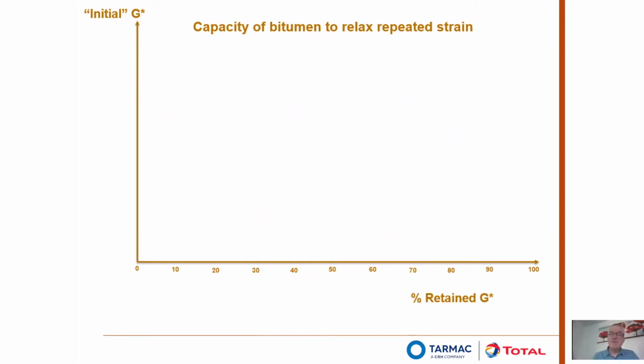So if we consider that, this is a test, again using the same equipment as the previous slide, where you stick together a top plate and a bottom plate. But with this one, you're applying a known strain to it. So you're moving it a certain distance, and again the bottom plate follows it, and you're measuring the amount of force required to move it. Effectively, what you're measuring is the G star, the complex modulus, but we can consider that as strain effectively.